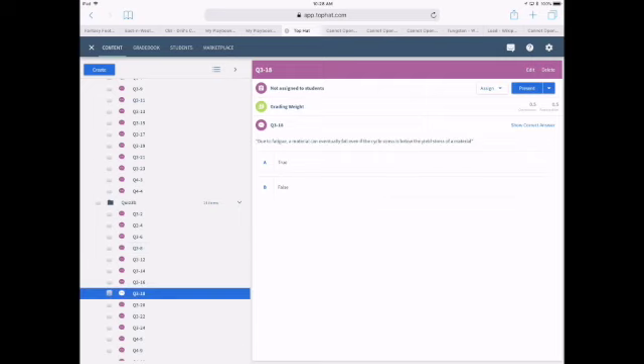So due to fatigue, a material can eventually fail even if the cycle stress is below the yield stress of a material. Is that true or false? So we were talking about the fact that yes, fatigue causes the cracks and voids to grow, which increases the localized stress. Once that localized stress goes above the yield stress of the material, it can fail. So the overall stress being applied can be much lower than the yield stress, which means that a material will eventually fail even if the cycle stress is below the yield stress of the material. So that would be true.